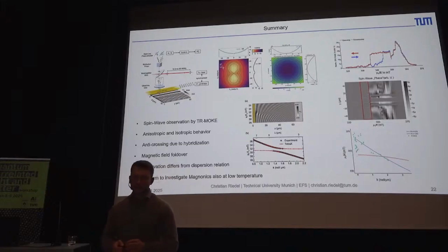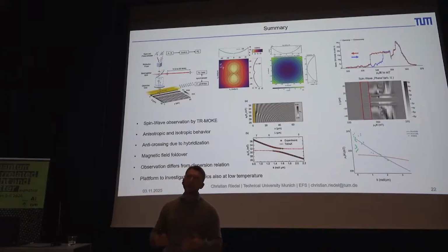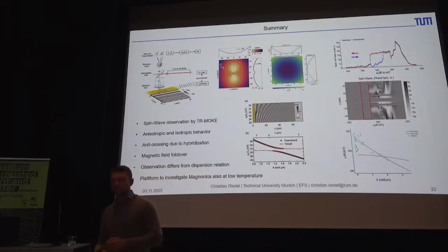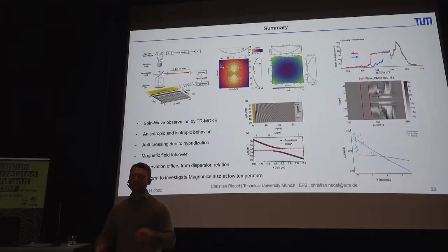Why we see this only in out-of-plane geometry but not in in-plane, for example, is that the oscillation amplitude of our spin waves can be much higher for the out-of-plane magnetization, because if your magnetization precesses, it's not limited by any surfaces, but it can precess in the film very easily. This is why we reach these high amplitudes, and this is why we come to the nonlinear behavior. We tried to model this with a Duffing oscillator, but it's not quite the same energy landscape, so we have to call it Duffing-like or whatever. That's why I never mentioned Duffing, but just nonlinear oscillator.